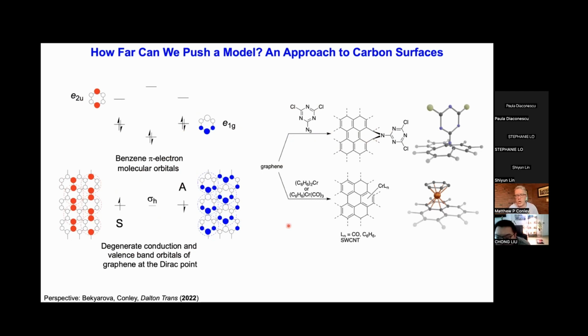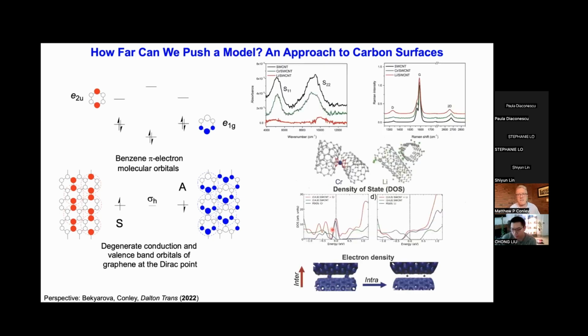And what he was able to show is that if you complex something like bis-benzene chromium or benzene chromium tricarbonyl, you can generate well-defined graphenes. And if you put those on single-walled carbon nanotubes, you can conserve the optical properties, and you can get very interesting conductive networks that are different from what you see with just doped lithium carbons, because you're now promoting not just intratube electron transport, but intertube electron transport, because this chromium site is very good at bridging the bands of two single-walled carbon nanotubes.